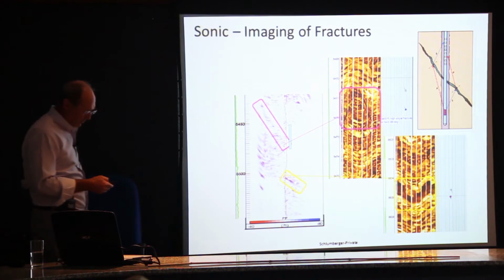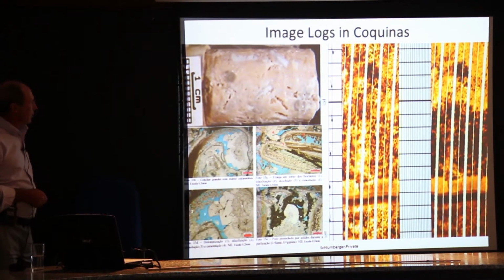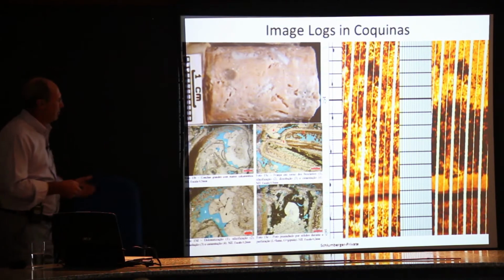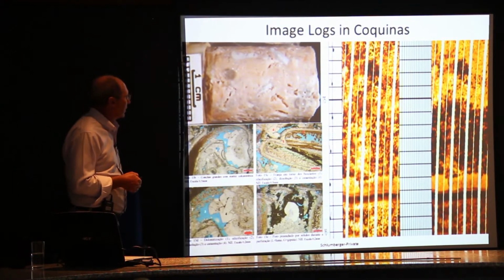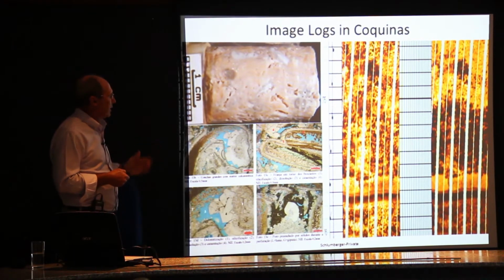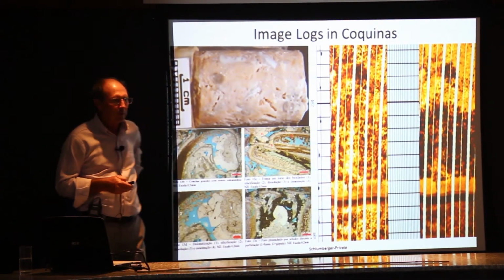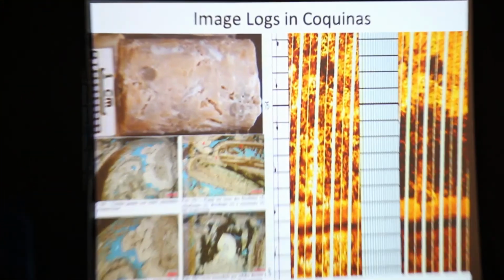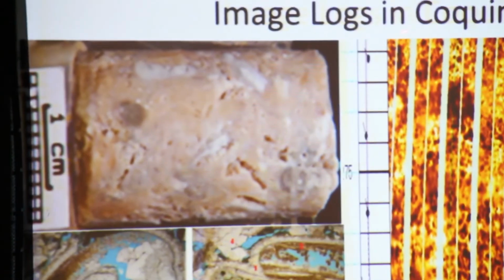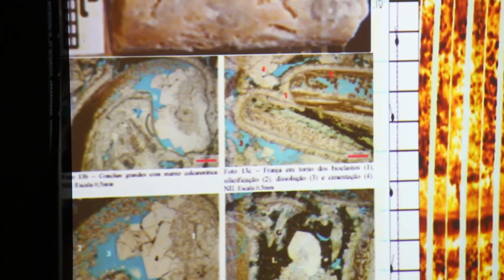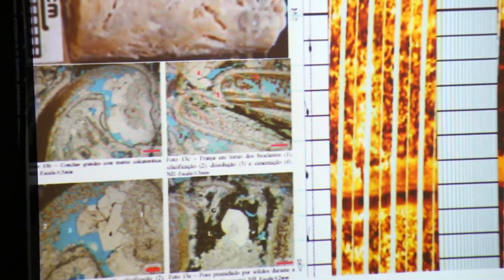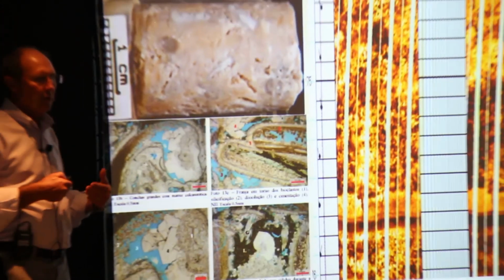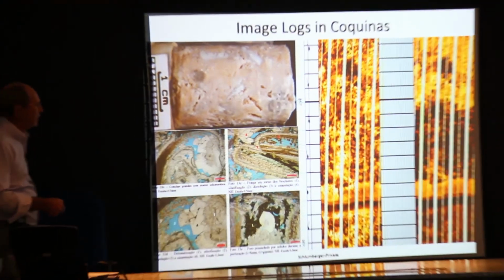So we were talking about images and acoustic and electrical response, and images are also helpful for looking at the types of carbonates. So remember that log we looked at earlier, we said there was one zone with coquinas. Here is an image log in a zone where you have coquinas. So the dark spots, they're an indication of this vuggy porosity. The dark spots are indications of low resistivity or higher conductivity.